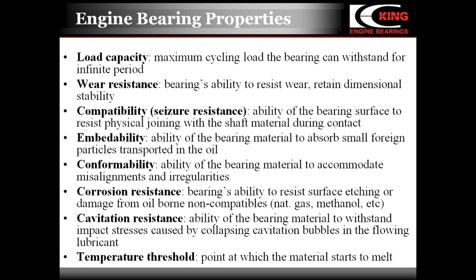Such a combination of properties may be achieved if the bearing material has a composite structure. Actually, all bearing materials have a composite structure. It means that they are built of a relatively strong base, like copper or aluminum, combined with a solid lubricant in the form of either a thin overlay or small particles incorporated in the base material.